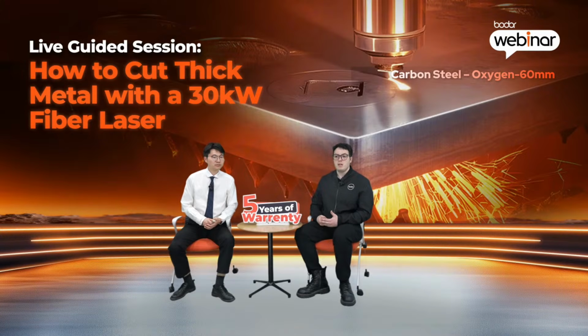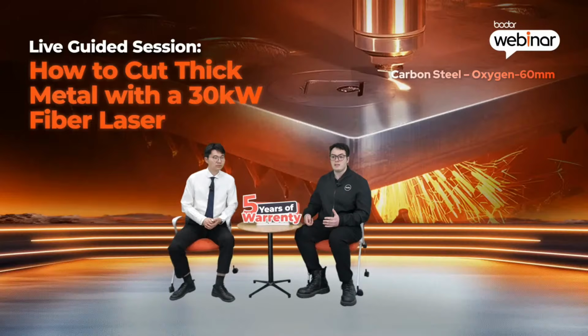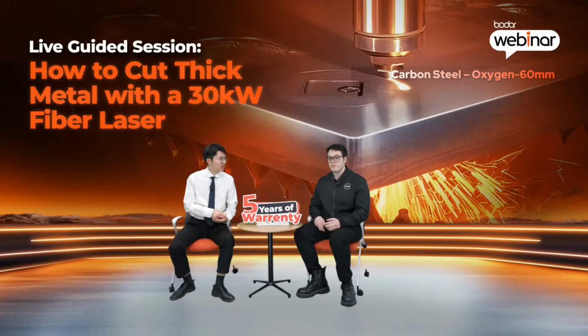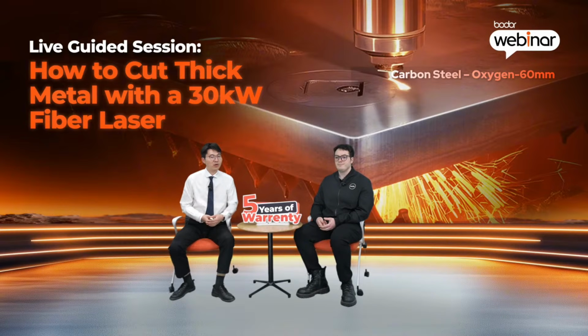If the process becomes stable, you can try negative focus. In that case, the focus is set to minus 25 millimeters. The cutting speed ranges from 0.5 to 0.8 meters per minute. And we are using a single layer 3.5 nozzle. This increases cutting strength, but it also makes the process easier to lose control. So for 60 millimeters, you don't start with the speed, you start with stability. And let's look at the real cutting results with the cutting demo video.